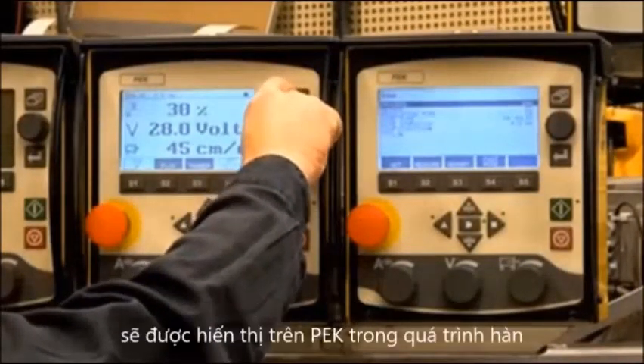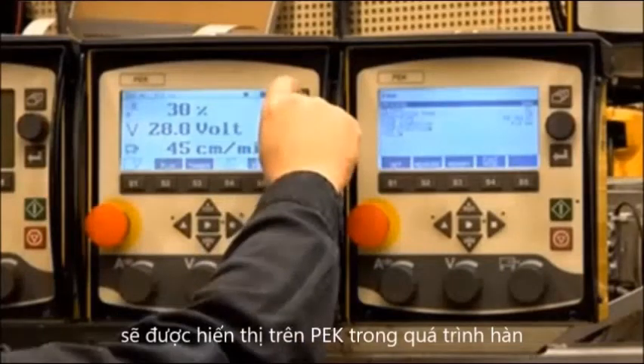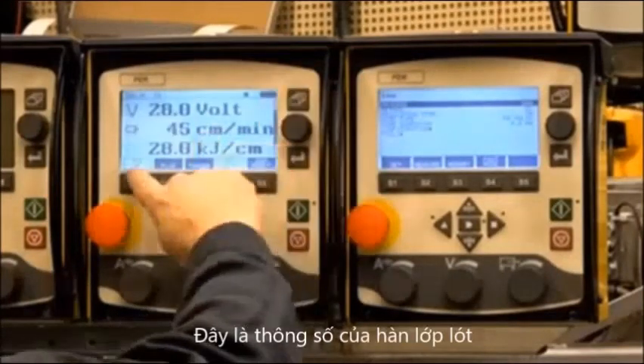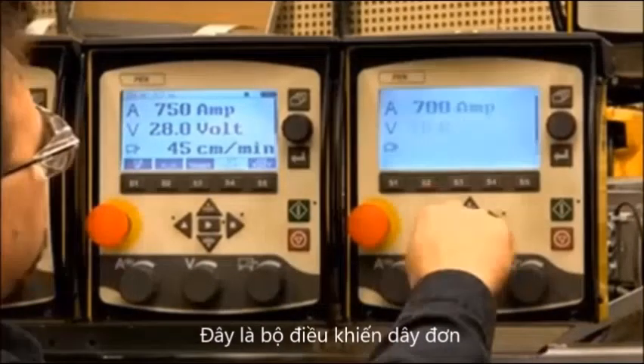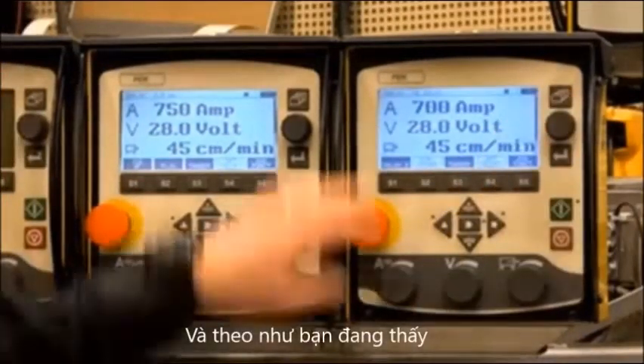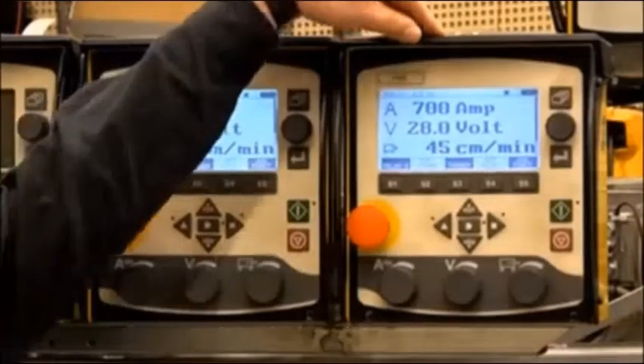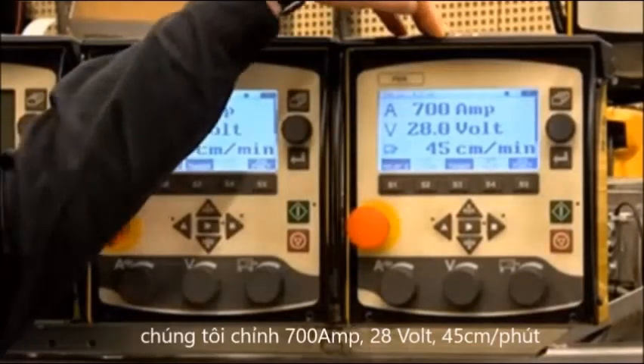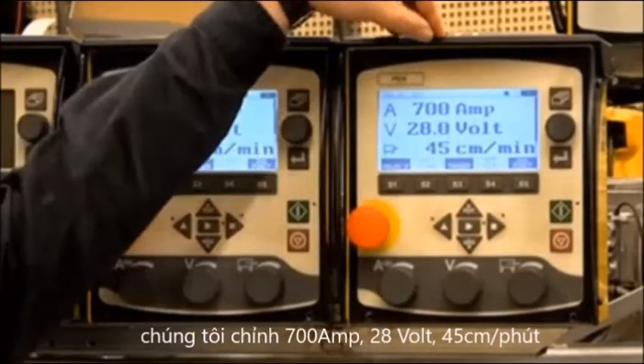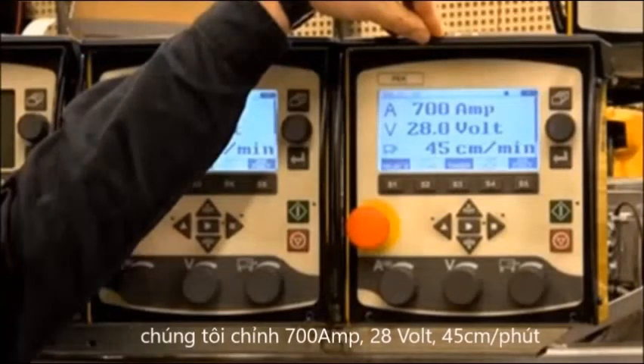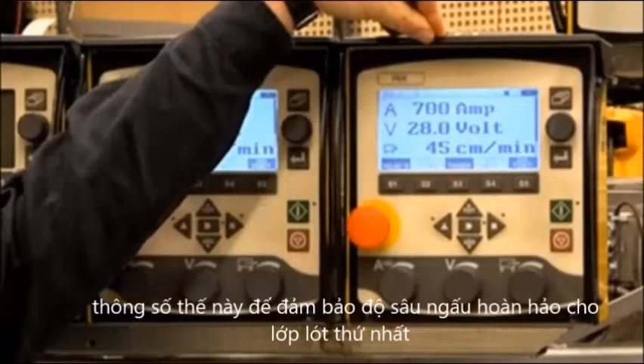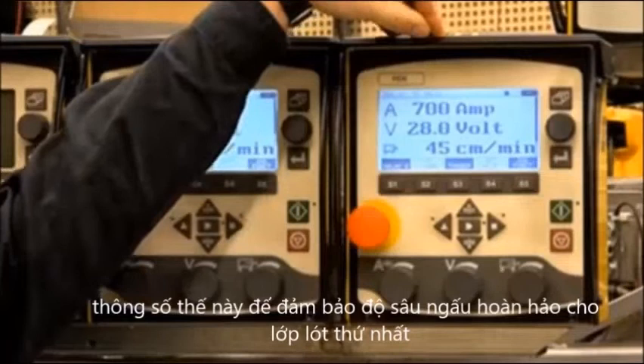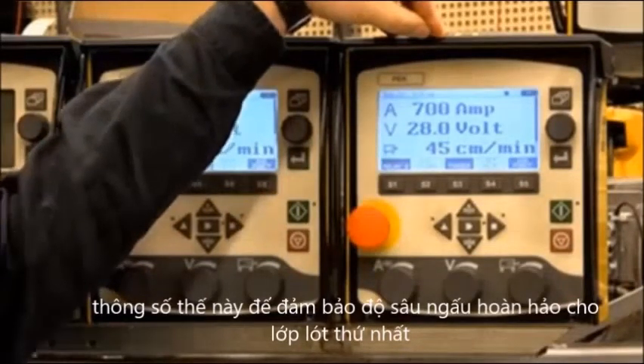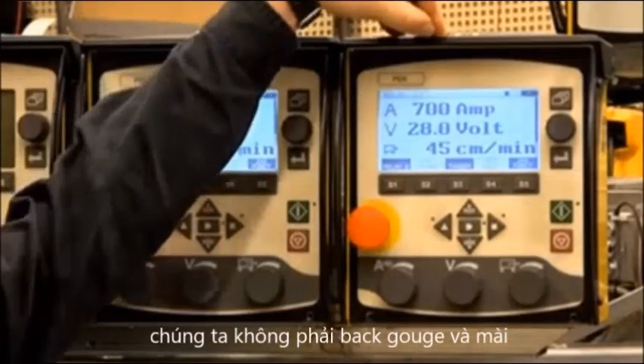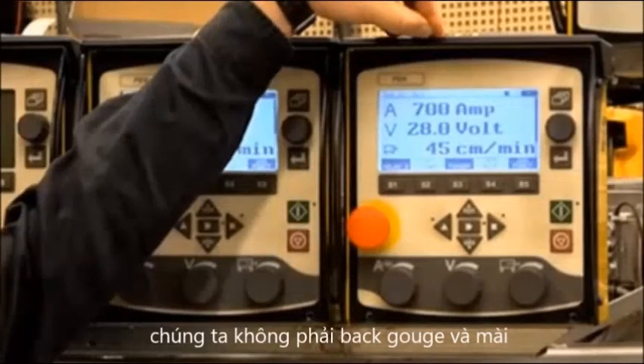what we expect to see during the welding, and obviously that there will be a root pass with a single wire, and as you can see here, in the first run, we will run 700 amps, 28 volt, and a speed of 45 centimeters per minute. That is for the first root pass, to make sure that we get a proper penetration, because I mean, we don't want to back gouge, we don't want to grind.